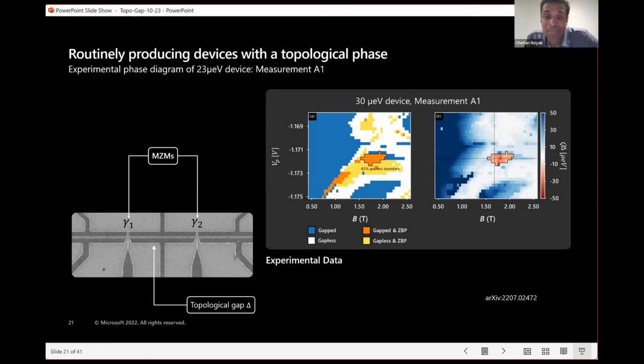Just like the phase diagram we get with simulated data, here's the phase diagram we get from real experimental data. Here is a region where the system is gapped. There are zero bias peaks. The boundary is gapless or predominantly gapless. Out here is the trivial phase, and the white and yellow is where you're in the critical region in this disordered system. On this color scale showing the size of the gap, here's the region that we identify as topological. It's a gapped region surrounded by gapless areas in the phase diagram, and there are stable zero bias peaks here. So this is what you really expect a topological phase to look like in a system like this.